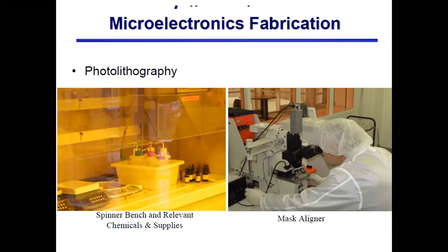First, you have to clean your wafer. You have to wash your wafer with isopropanol. In fact, this bench, you have to wash it with isopropanol. You have to wash it then with deionized water. In the clean room, all water taps will be deionized water. So first you wash it with isopropanol, then with the DI water, and then you dry it with the nitrogen gun. Nitrogen is an inert gas. It would not react with any chemical on your wafer.